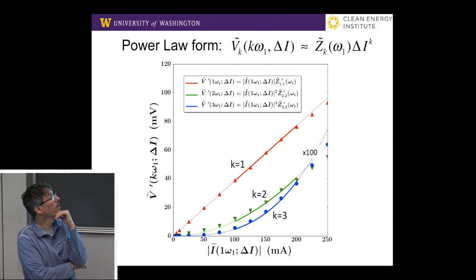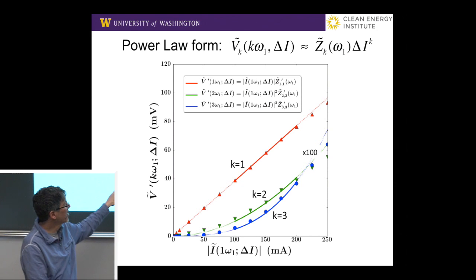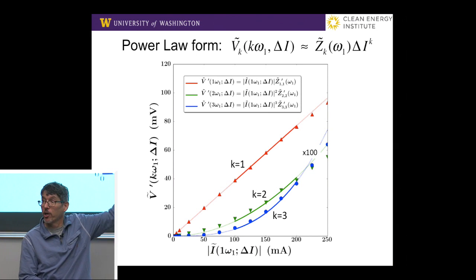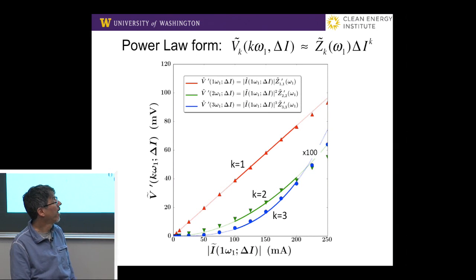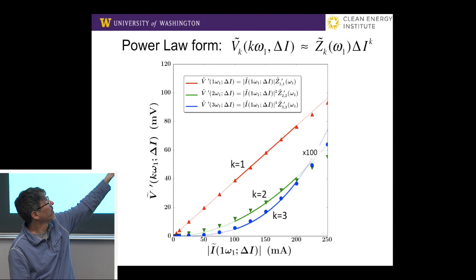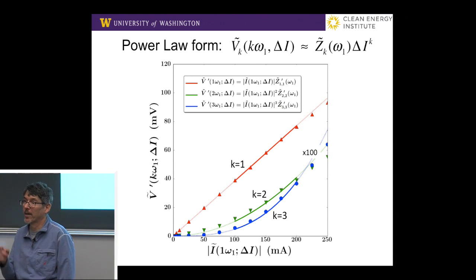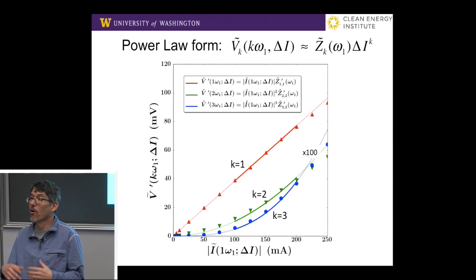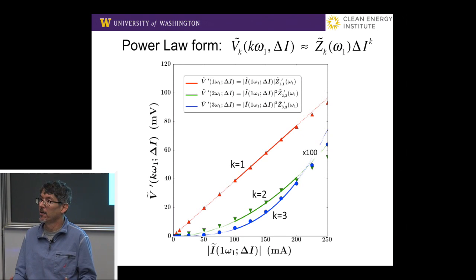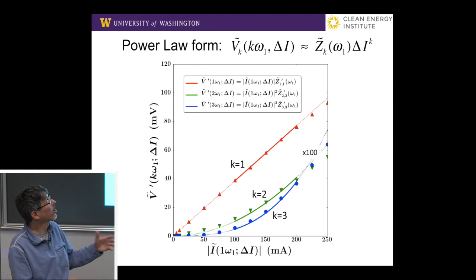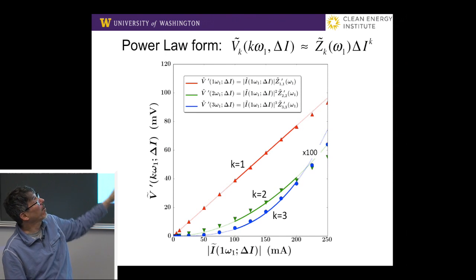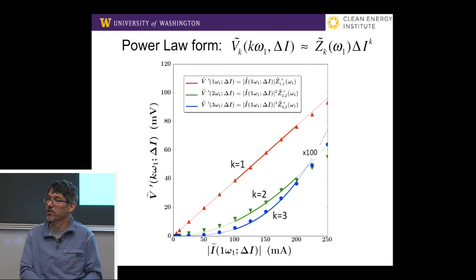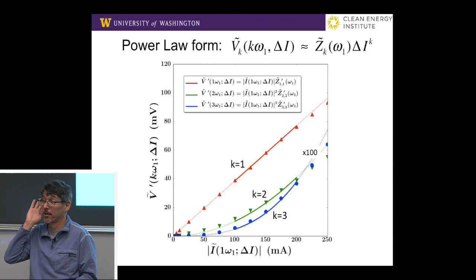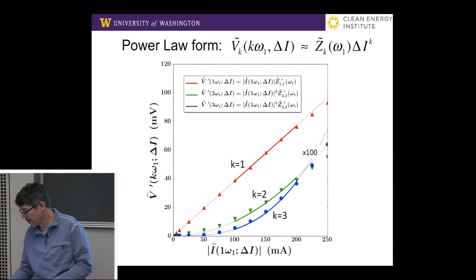And then if we do the third harmonic, K3, we see it starts out lower, but it grows cubically. And there we go. And so the coefficients in those regions that I'm showing you for K1, K2, and K3 are going to be the frequency-dependent dispersion coefficients. So our experiment is, let's vary the frequency of the excitation, and let's listen to the linear and nonlinear response of the battery.